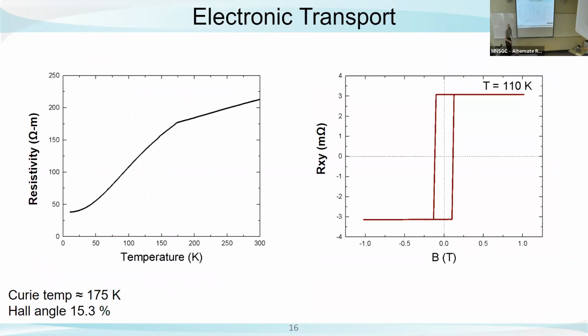And then since we did get a crystal, we were able to do some electronic transport. As you can see here, if we cool our sample, our resistivity goes down. That's showing us that the material is a metal, which is exactly what we want. There also is a tiny kink in the graph at about 175 Kelvin. And if you remember back from my previous slide, that is the Curie temperature for the material that we were trying to grow. And then at 110 Kelvin, we get that beautiful hysteresis loop that we would also associate with being a Weyl semimetal when we look at our magnetic versus our Hall measurement.